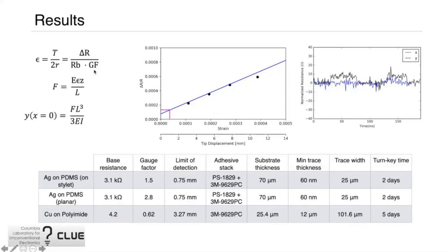Overall, with our noise reduction techniques, the devices we fabricated have a limit of detection of 0.75 millimeters and demonstrate linear behavior up to 9 millimeters in tip displacement. In general, our device has higher sensitivity than what is possible with flex PCBs, which typically have a 100 micron wide trace limit and are typically on a polyimide substrate.